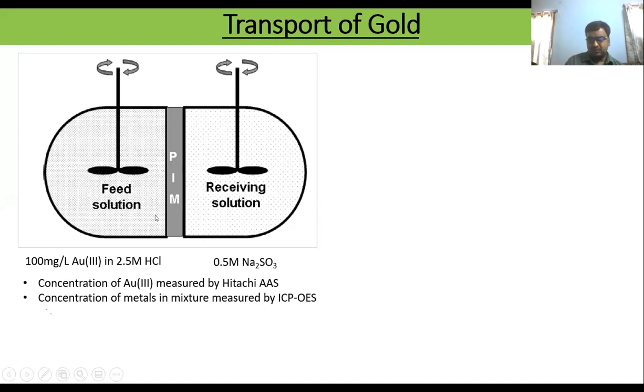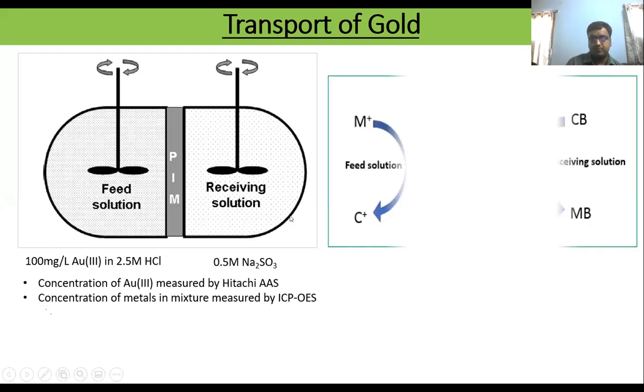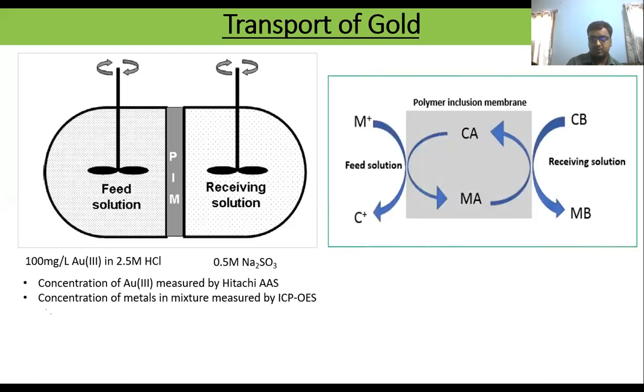And this is the transport cell. So gold from this side moves towards the receiving side. And we measure the gold concentration using AAS. But when we have a mixture of gold with other metals, then we use ICP-OES for the measurement. So this is how it works.